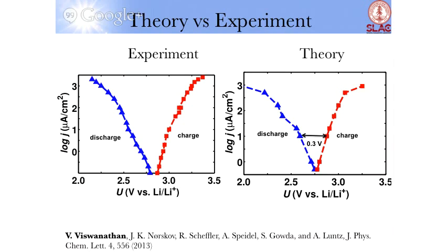But the take-home message essentially is that the cycle efficiency of this battery is really good because you only pay a penalty of about 0.3 and you get about a 2.8 volt battery, right? So that's remarkably high electrochemical efficiency compared to what we have with oxygen and proton, where you pay a 0.8 volt penalty for something that only gives you about 1 volt. So what that means is at least the cycle efficiency is really good.